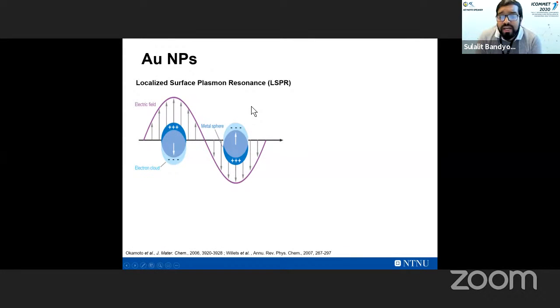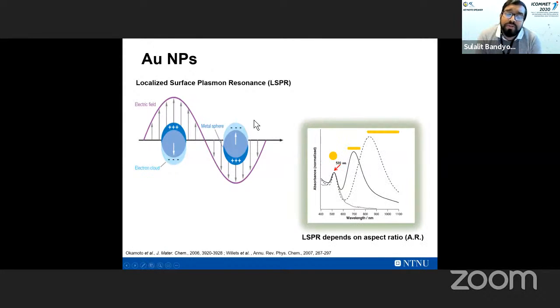So what it literally translates to, for those of you wondering, this is a fundamental property, how do we make use of it, is that if you are detecting gold nanoparticles using UV-vis spectroscopy, you'll be able to see that there is a huge difference the moment you change the size and the shape. So for a typical gold nanoparticle, this LSPR peak is located around 520 nanometer.